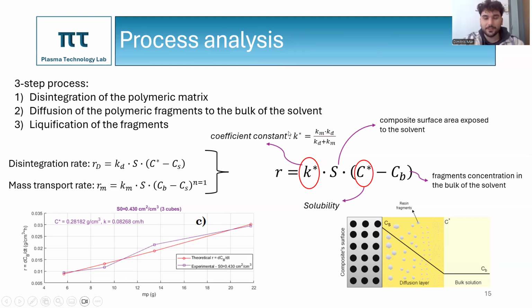This equation is a function of the coefficient constant that includes the disintegration constant and the mass transport constant. It is also a function of the composite surface area exposed to the solvent, the solubility of the material, and the fragment's concentration in the bulk of the solvent. And basically, the two parameters that determine the efficiency of the composition are the coefficient constant and the solubility of the material. That's why we made an effort to fit our experimental data in this equation. And we can see an example right here. And we have a really good estimation about the coefficient constant and the solubility and how those two change with different parameters of the process.